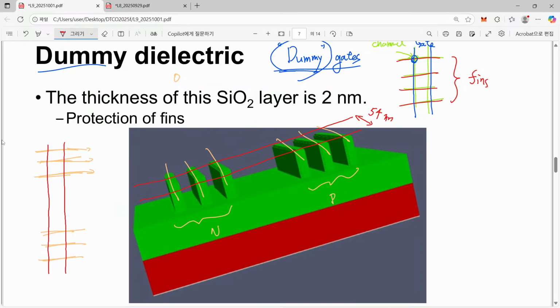Okay, so simply speaking, although we are saying that this is corresponding to 7 nanometer technology, 7 nanometer is not your gate length. Your gate length is much longer, 20, and the CPP is not a multiple of the number 7. So 54 divided by 7 doesn't give us an integer number. So there is no 7 in this case. Maybe you can make some relation between fin thickness and node number.